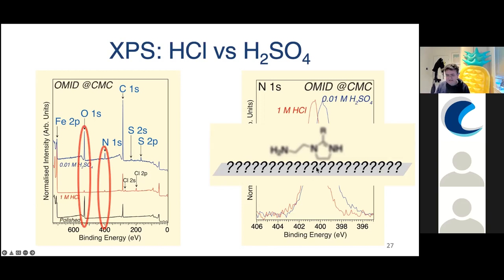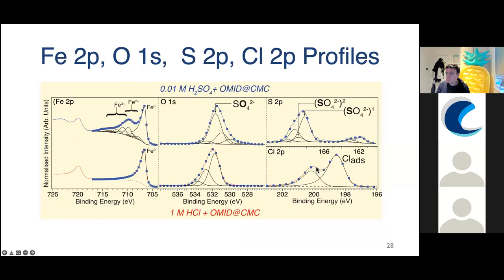So what about the interface itself? What about the substrate termination? So again, we're relying on iron, oxygen, and in this case, sulfur signals, and looking at their profiles to look at this substrate. Here I'm comparing data from 0.01 molar sulfuric acid with the data we've already shown for 1 molar hydrochloric acid, both with OMID at CMC. If you remember, in terms of the iron signal, we just saw metallic iron, whereas a key difference here for the sulfuric acid, we see strong signals, in particular due to Fe3+. We also see some Fe2+, but the main signal is from Fe3+. So it's no longer metallic iron at the surface, but it's some sort of salt or oxide.